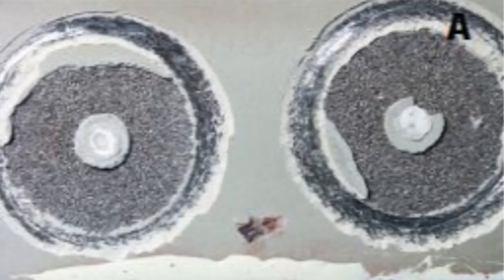Now we look at what the impregnated slag does to the adhesion. This is a picture of the slag blasted surface put to the adhesion test and failed. You can see that the dollies popped off of the slag blasted surface in this test. We now test the GMA garnet surface. There is strong adhesion with the GX GMA garnet, where the glue holding the dolly failed long before the coating would ever come off the surface.